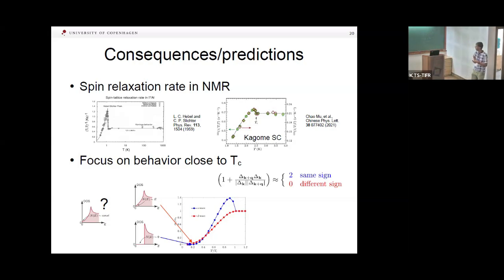A nuclear spin relaxation rate as measured in NMR experiments. And here I have just put up some data from aluminium from the early days. So at high temperatures, you have a constant spin relaxation rate. Once you hit Tc, then there is this increase, this Hebel-Slichter peak. And then once you reach low temperatures where there are no quasi-particles available, then the spin relaxation rate actually goes to 0.